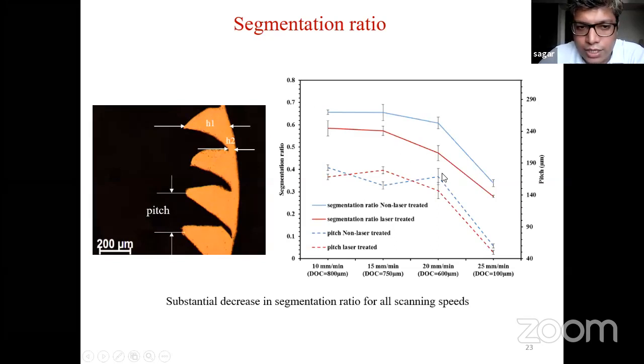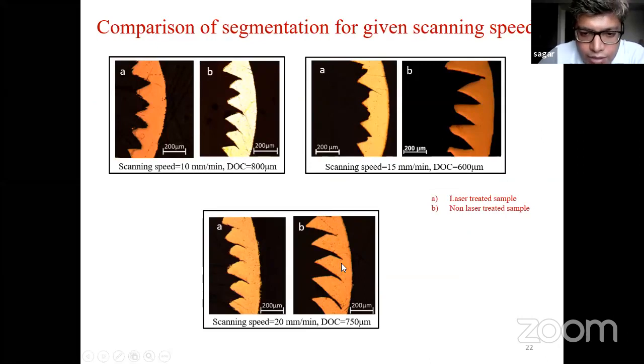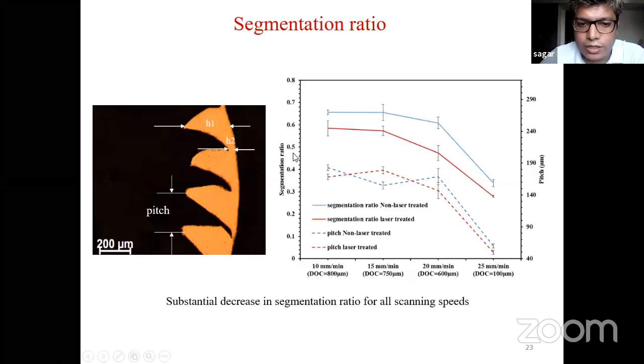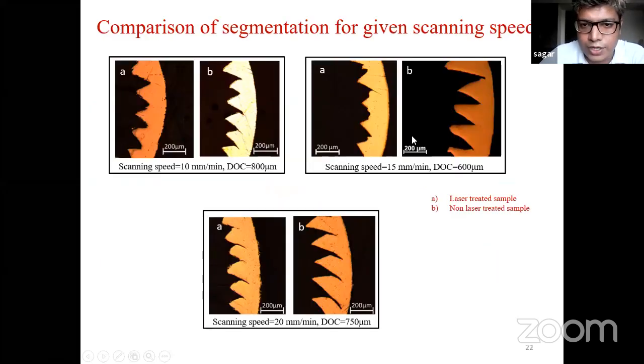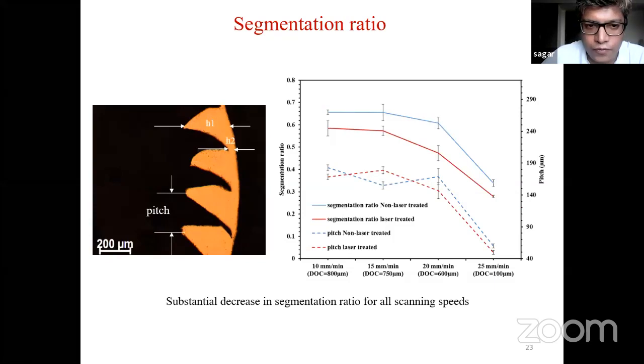So the reduction in segmentation ratio indicates that the plastic deformation happening on the rake surface has been reduced. When the plastic deformation is reduced, the heat carried by that plastic deformation, which is considered as loss, has been reduced. Once the loss has been reduced, the force variation also has been reduced. Once the force variation is reduced, you will get lesser vibration on the cutting tool, thereby you could improve the tool life and the machinability of that material. So this was the crux of it, right?